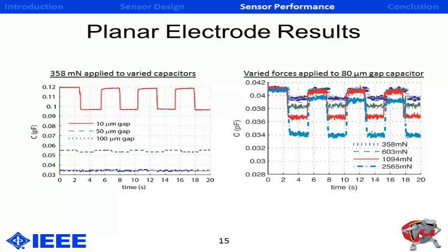On the right-hand side, we have a similar plot, also in the time domain, but for a single capacitor of 80 microns, and various forces are applied. So as the force increases, the change in capacitance also increases. It's interesting to note that only after 1 cycle for the highest load case, there is noticeable hysteresis during offloading.